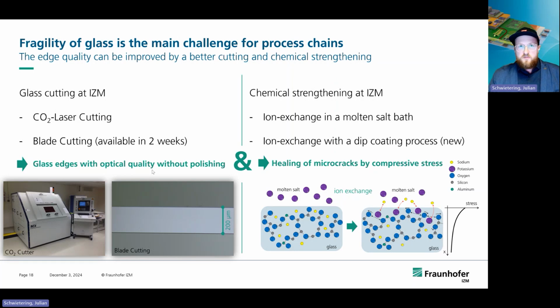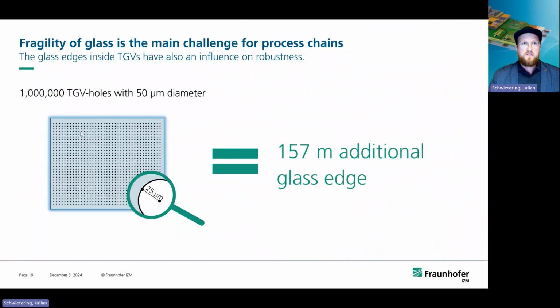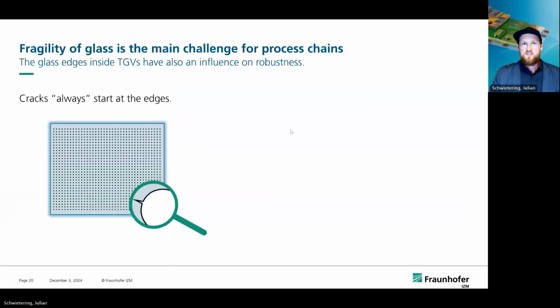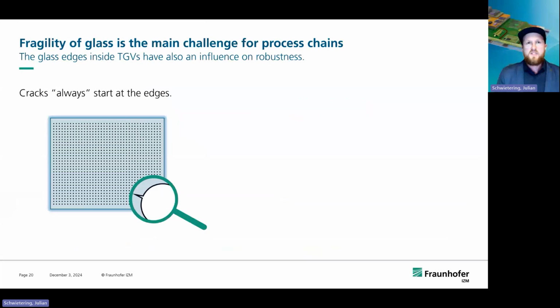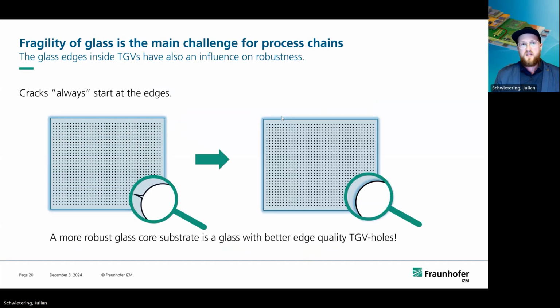But the challenge is not solved now, because the glass edges inside TGVs, and you can have a lot of TGVs in a glass core substrate, also have a strong influence on the robustness. As an example, if you have 1 million TGVs with 50 micrometer of diameter, then you have 157 meters of additional glass edge. So it's the same story. If the cracks always start at the edges, then a more robust glass core substrate is a glass with better edge quality in the TGV holes.